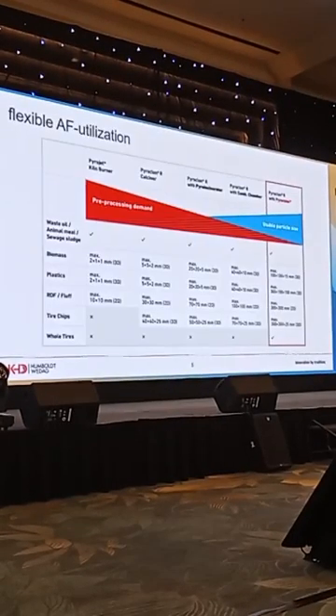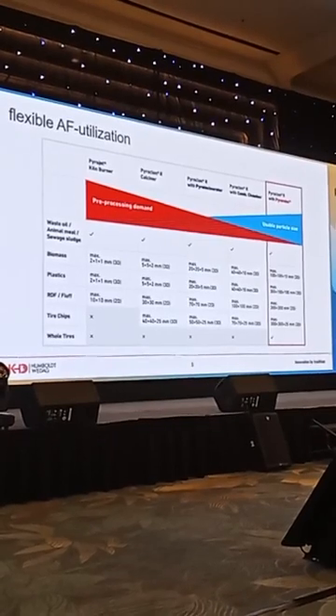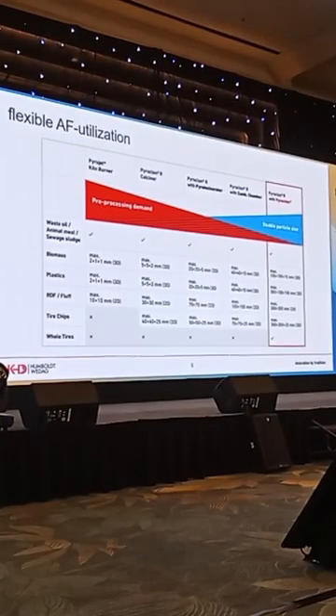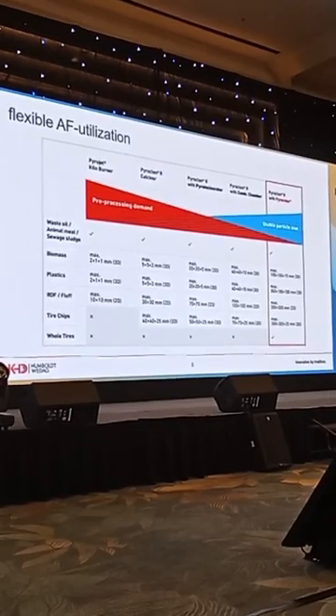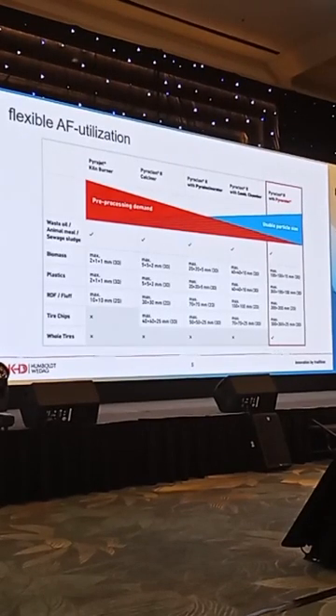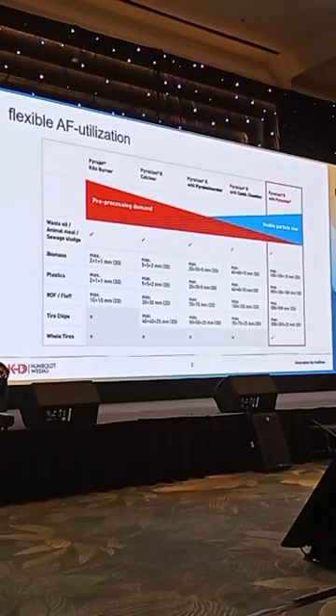So on the next screen you see, for the alternative fuel utilization from the KHD company, the overview of the points where you can use alternative fuels. We are able to burn even alternative fuels in the rotary kiln by feeding it to the pyrojet burner or maybe a satellite burner installed next to the kiln main burner. But you can see already in the sketch, we are really limited in the size of materials. We are here in the range of, let's say, 2 to 10 millimeters, depending on whether it's 3D or 2D material. And this is really limited because this material has to be pneumatically conveyed to the burner. Otherwise, you cannot feed it to the main burner itself.